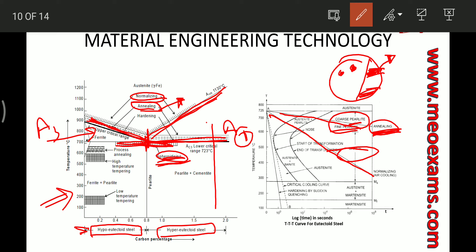For hardening, the heating process is similar to annealing — above A3 for hypo-eutectoid steel and above A1 for hyper-eutectoid steel. However, the rate of cooling must be greater than the critical cooling rate, which touches the nose of the CCT curve. The specimen must be cooled fast enough to miss the nose, forming a martensite structure. Martensite is very hard and brittle, making further work difficult.